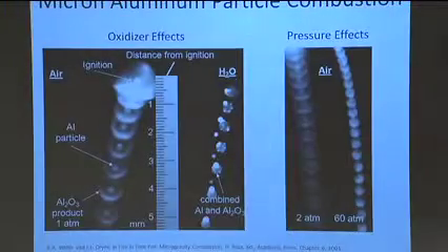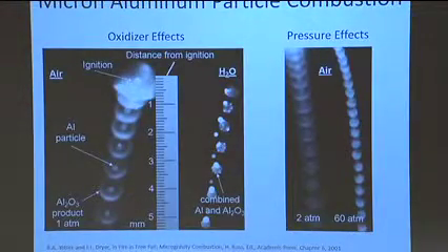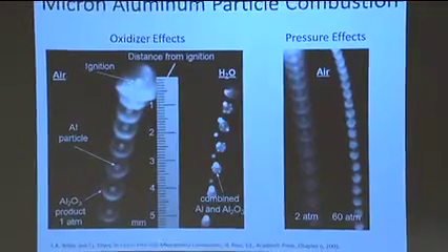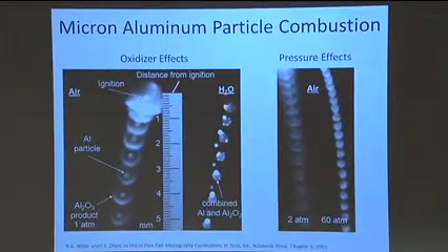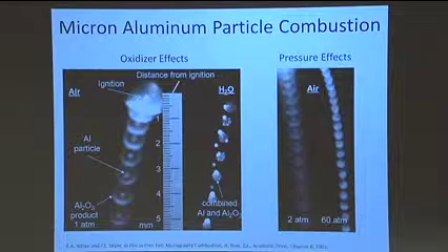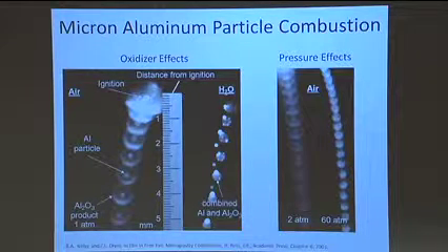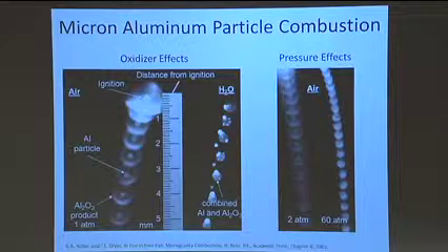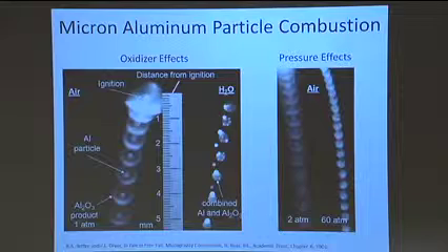Okay, and to illustrate that, I show some pictures here of the effect of oxidizer and pressure on single particles of aluminum, which are at the micron scale. Okay, so here, this is an experiment where you're seeing a single droplet that's being ignited by a laser. It's falling, and what you see, in this particular case, is that the Grashof number is very low, the Reynolds number very low for this particle. So this is a strobed image. You're seeing the same particle here.